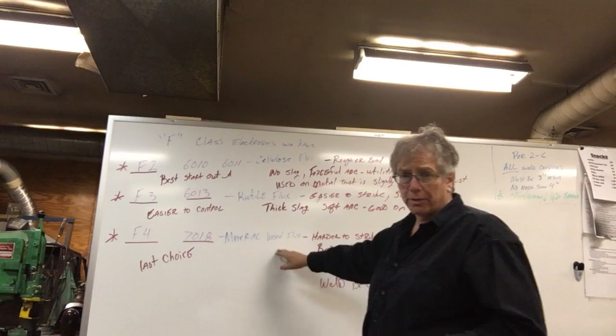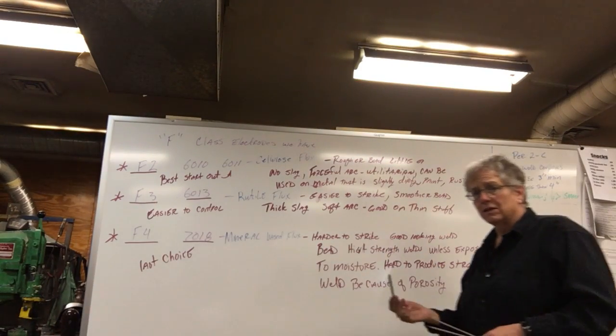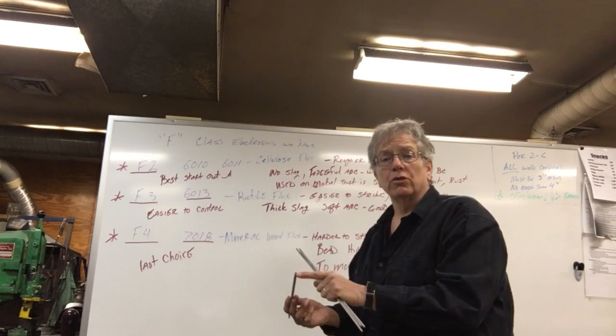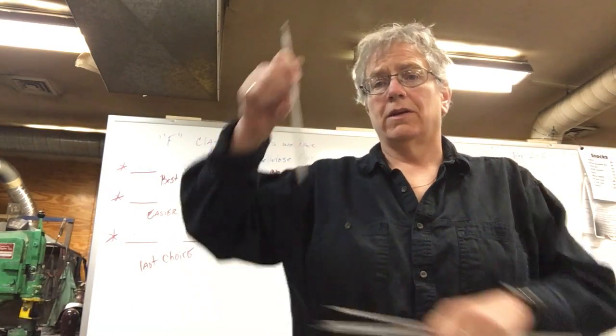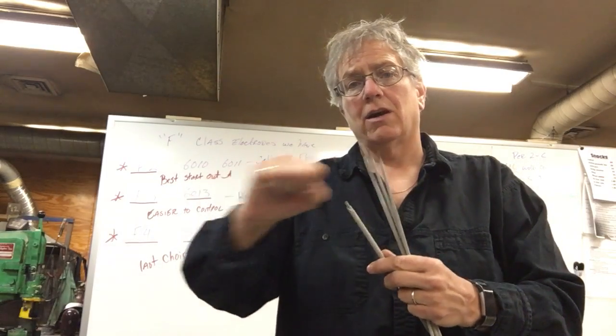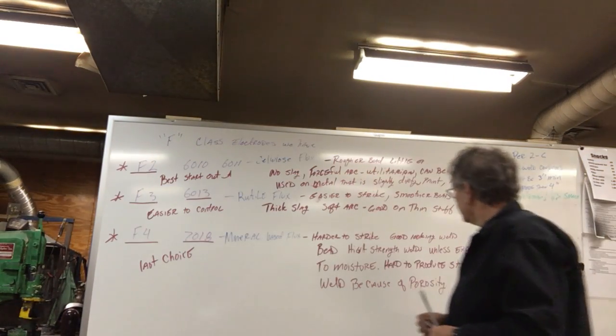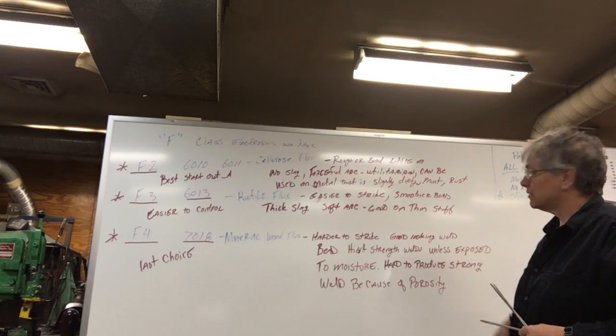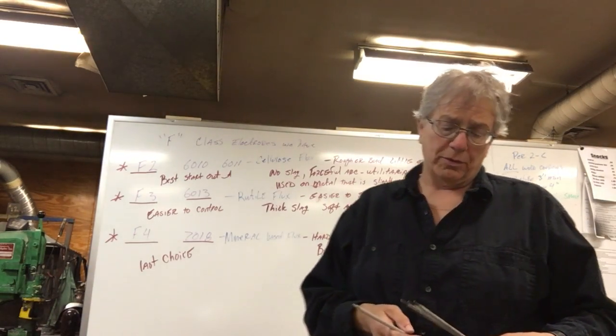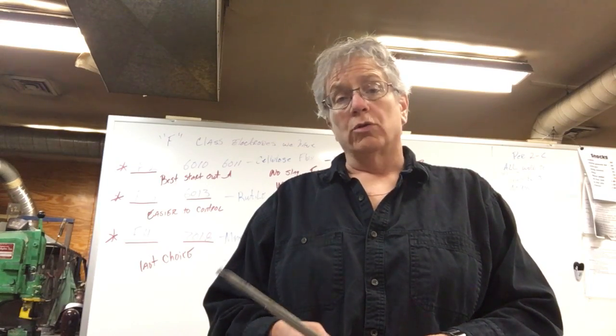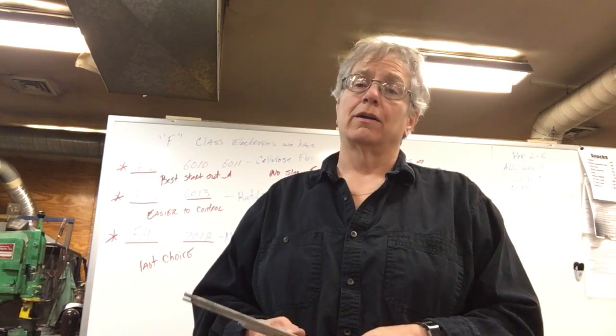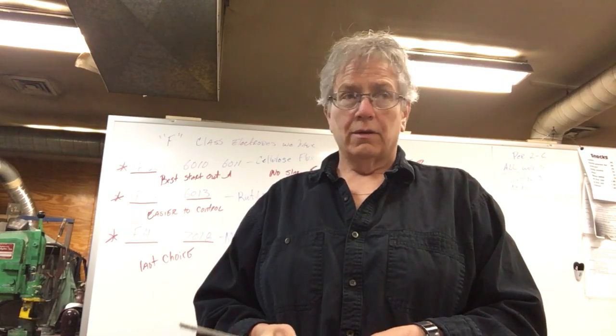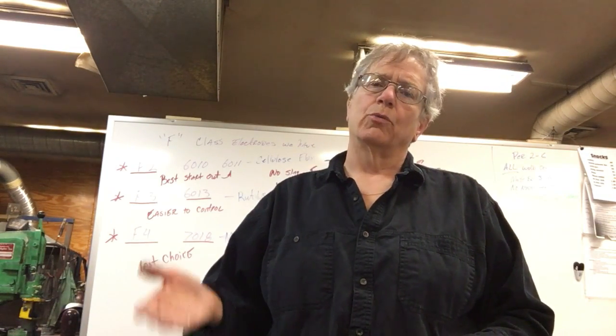7018 or the F4 class. The F4 class is a mineral-based flux. It's harder to strike because it gets a heavy slag on the end. So when you go to strike your arc, you need to smack the very end of it down on the table, or take a file and file it off a little bit. Then it will strike your arc. It does produce high-strength welds unless you expose it to moisture. Some of them that we have in the shop have a -1 or an H4R on there. That means that they can be exposed for 4 hours. Now, exposed to moisture means outside of the rod oven, okay? The rod oven keeps them warm, keeps the moisture out. Moisture causes hydrogen cracking, it also causes porosity, right?